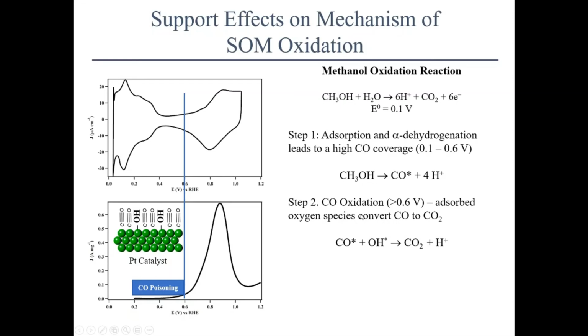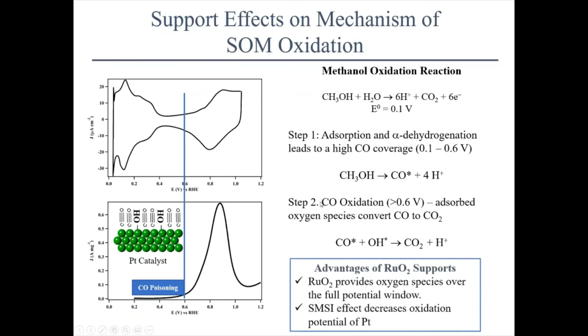So the CO oxidation requires some kind of oxygen species to be adsorbed, and then we can get effective methanol oxidation catalysis. Part of the reason why we selected the ruthenium oxide support was because this provides oxygen species over the full potential window. In essence, ruthenium oxide is an oxide. And also we get this SMSI effect where we can make platinum slightly more oxophilic, and it oxidizes at a little bit lower potential. So we can bring down this onset potential a little bit closer to the thermodynamic potential.